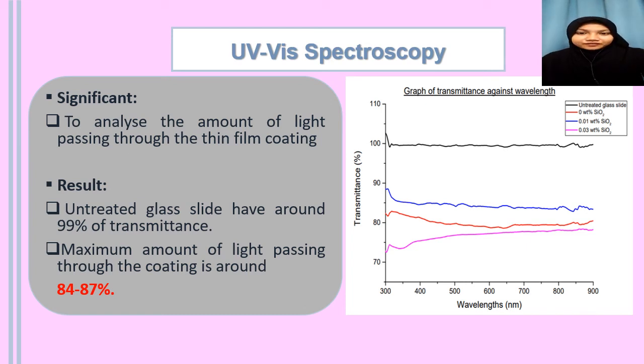Okay, by referring to the result from the SEM, you can see that there is agglomeration inside the thin film coating. The agglomeration will reduce the transparency, so it will reduce the percentage of light transmitted. It also happened because there is a larger difference of refractive index between the thin film and the substrate. With a larger difference of the refractive index, there is a high tendency for a light scattering effect.